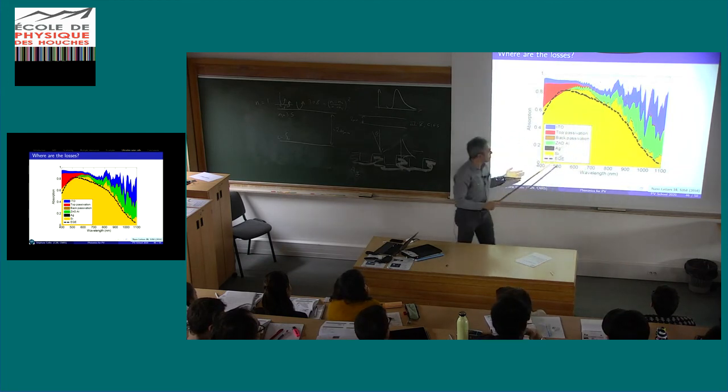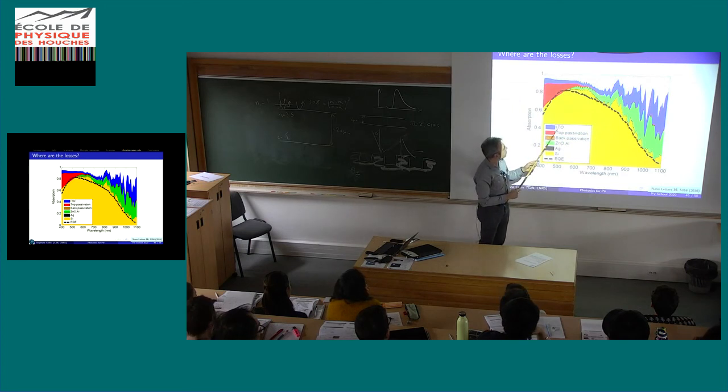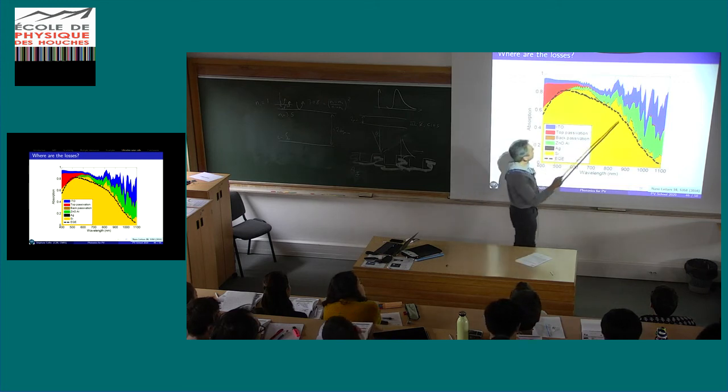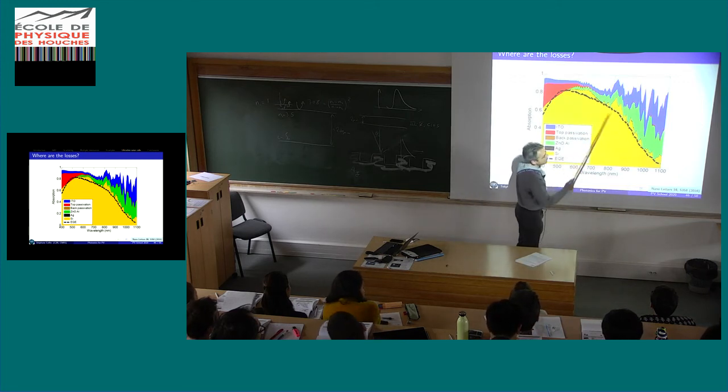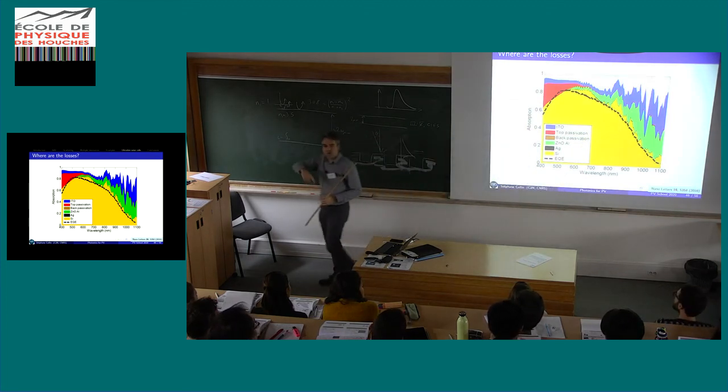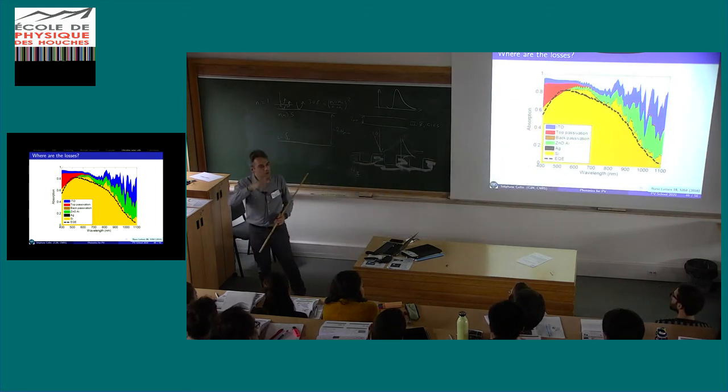But to make all the cell, we have used ITO. Top passivation, I think it was amorphous silicon. And zinc oxide at the bottom between the silicon and the silver back mirror. And so you see that all these layers induce parasitic absorption. And if you increase the optical path by a factor of 10, you also increase parasitic absorption.